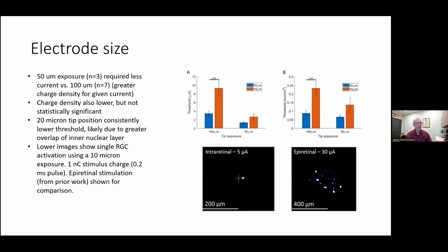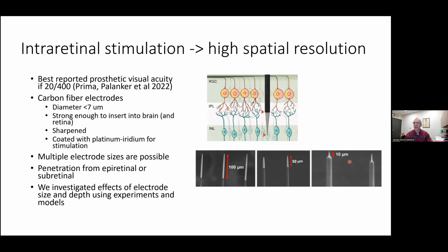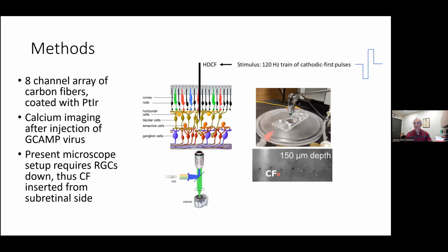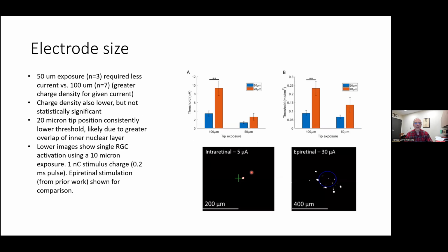And then, interestingly, this was a finding that was repeated several times, though I can't say it's generally our result. It's intriguing to note that with the intraretinal stimulation using a 10 micron electrode, so that's this one, this very small electrode, we inserted that into the retina as well. We could achieve a single retinal ganglion cell resolution. So you can see that this approach has the potential to really improve the stimulation resolution.